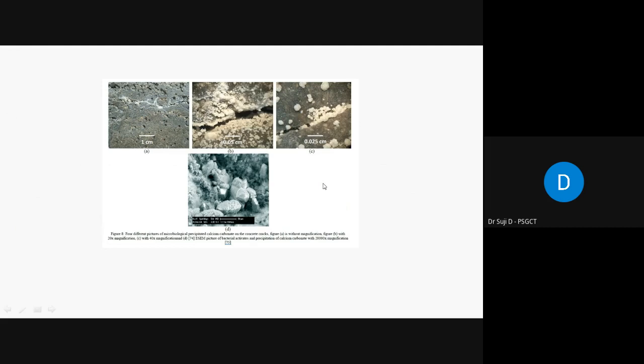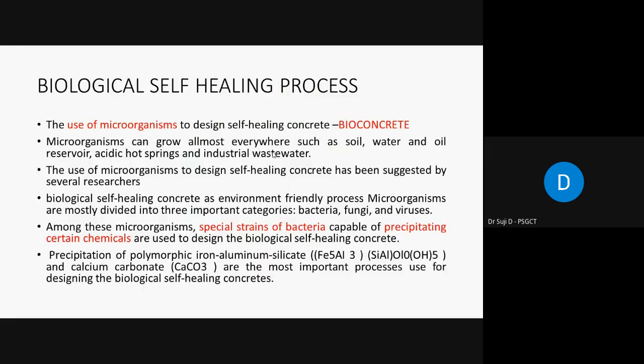So this is the SEM micrograph, a SEM analysis of a conducted research. This research shows that there is formation of new phases after the initiation of crack. So this is the formation of crack, and once microorganisms are present in the concrete, due to microbiological precipitation, calcium carbonate is precipitated into the crack, and it heals the cracks, right? So this is the SEM analysis of research conducted by some researcher.